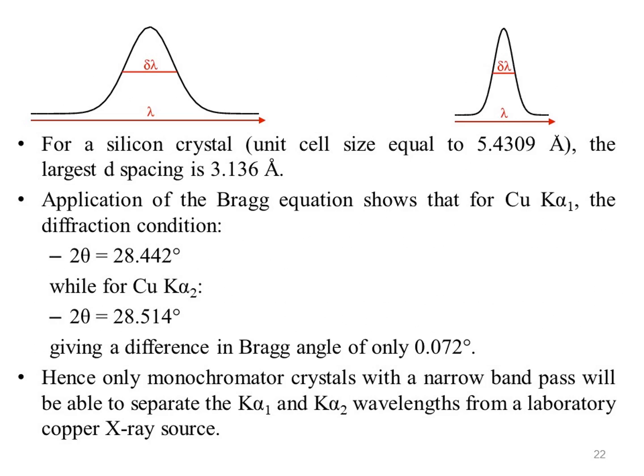The monochromator works by reflection of the wavelength that obeys Bragg's law for the particular d-spacing of the monochromator. For a silicon crystal, which is cubic, with the unit cell size equal to 5.4309 angstrom, the largest d-spacing, which is from the 1,1,1 planes, is 3.136 angstrom. Application of the Bragg equation, that is n lambda equals 2d sin theta, shows that for